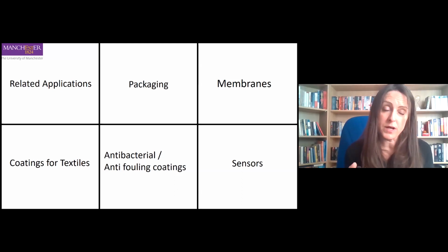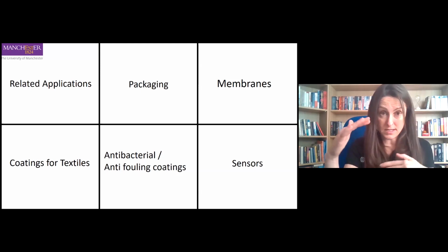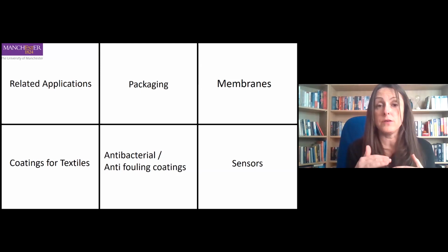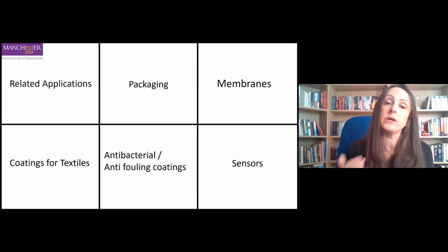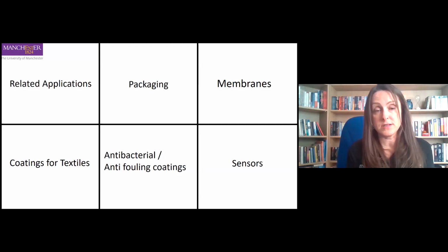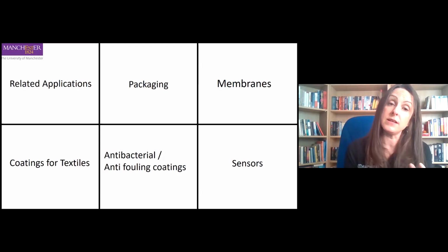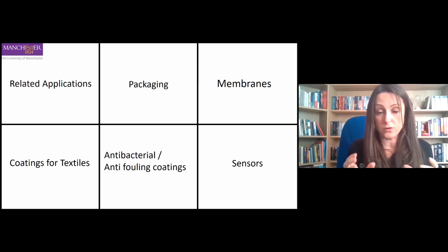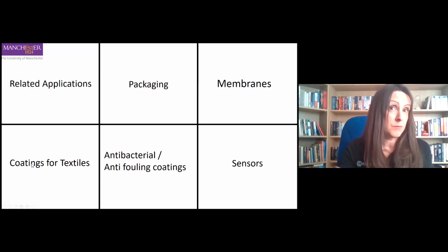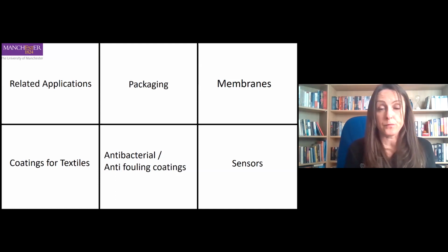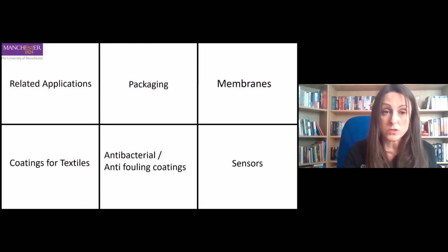One of the things we're doing when we're making membranes is we're tuning the pore size of the flakes within a pure graphene coating to allow different molecules to go through, sort of a filtration system, so you could get oil and water separation or desalination. And we can control pore size down to tiny amounts, 1 or 2 nanometers. Packaging, I mentioned briefly at the start. Again, we can make something that's a complete barrier, or we can tune the coating so that certain materials can go through, and certain materials can be kept out.